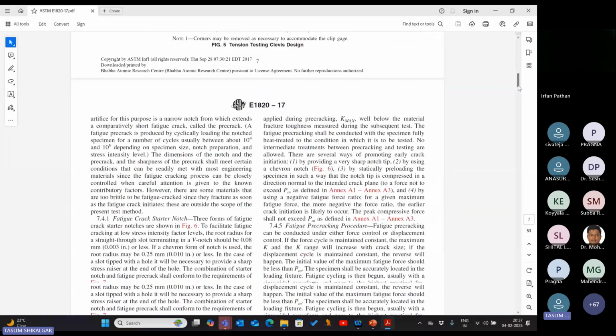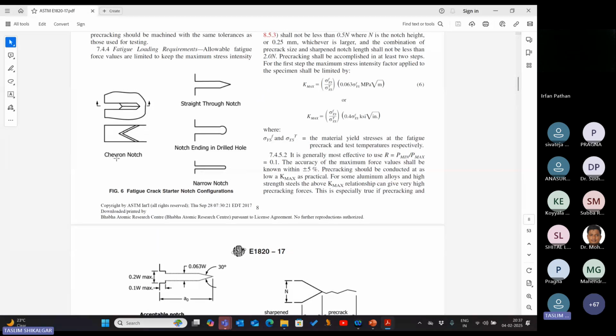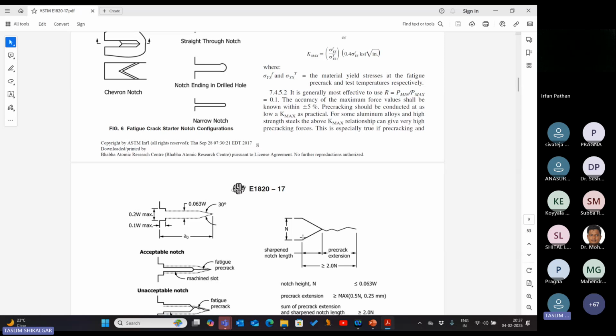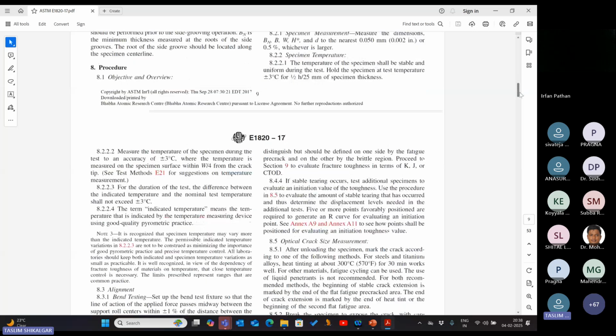One major important thing they use is the chevron notch. The chevron notch is a very helpful technique to generate a natural crack. Here, this is the initial crack they developed, and here they performed the fatigue analysis to develop the natural crack. The natural crack plays a major important role in getting the fracture property. But if you see these PSPT specimens, they are very small. You cannot perform the fatigue analysis to generate the natural crack. If you perform the fatigue analysis, plastic deformation will immediately happen. So you will get the wrong fracture properties from the PSPT specimens.